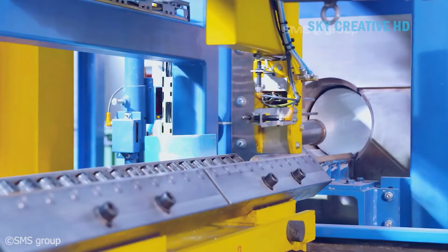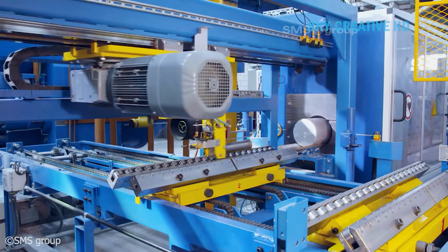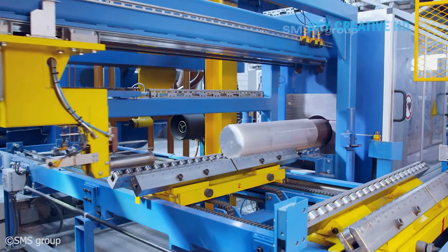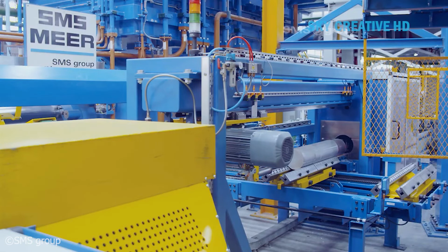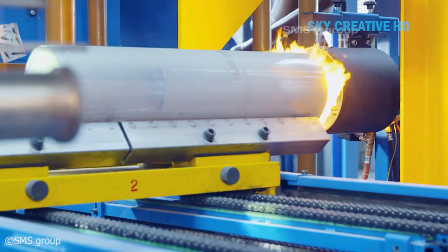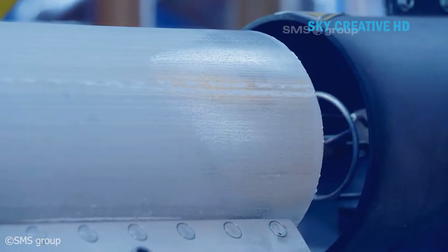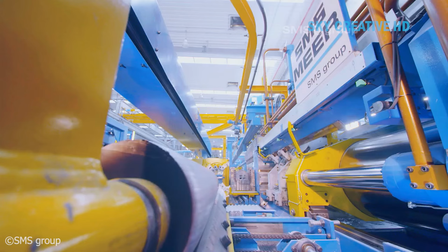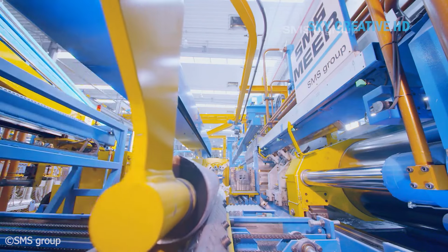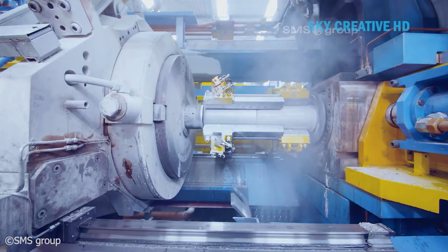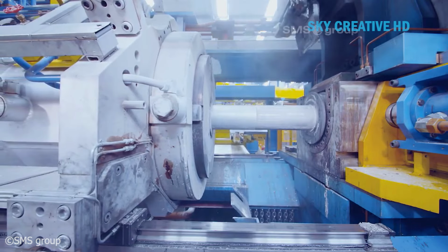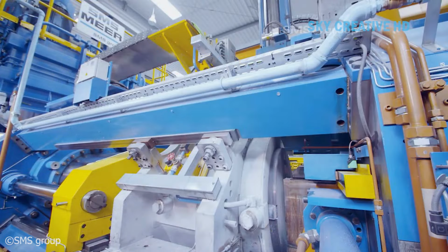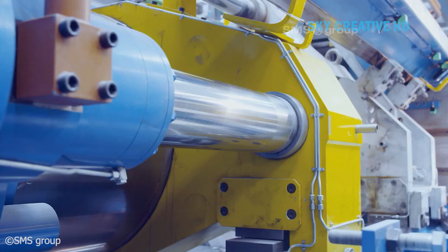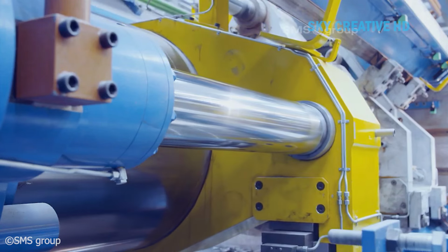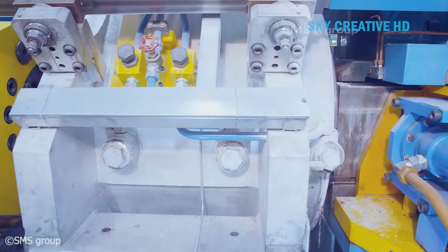The heated billet transfers to the extrusion press, and this is where the magic happens. SMS Group's hydraulic presses generate forces up to 10,000 tons or more. Imagine the weight of a small cruise ship concentrated into a few square inches. A dummy block sits behind the billet, and as the massive ram advances, it forces the softened aluminum through a steel die, much like squeezing toothpaste through a tube, except this toothpaste is glowing hot metal, and the forces involved are astronomical.